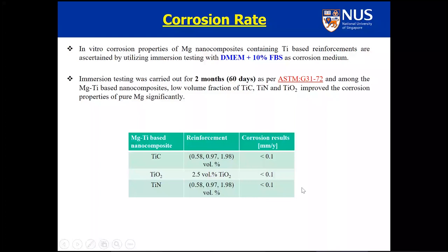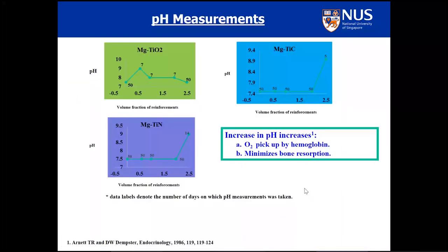So having said that, does it mean that all Mg-TiO2 systems or Mg-TiC systems or Mg-TiN systems will fit the bill? Yes, they may fit the bill, but we don't want the pH fluctuation, which is shown on the y-axis, too much in our body, in the microenvironment. So basically, if I take this last point at 2.5%, I know that I can get very good mechanical properties and the pH fluctuation is also very less. If I use TiC as a reinforcement, I choose 2%. And if I use TiN as a reinforcement, again, I choose 2% of that.